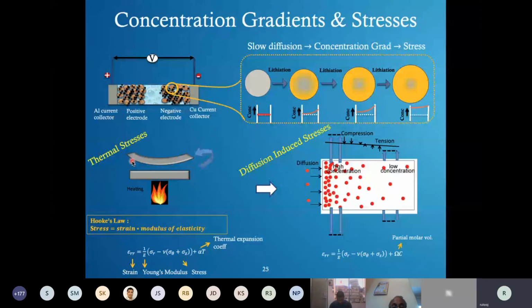Similar thing is happening here in the diffusion case. As your lithium atoms are diffusing in your electrode, there is higher concentration of lithium atoms on one side of the electrode, whereas there is lower concentration on the other side. In this particular case, there is lower concentration at the center and higher concentration at the surface. So the surface part wants to expand more, whereas the inner part, which doesn't have enough lithium concentration, does not want to expand at all.